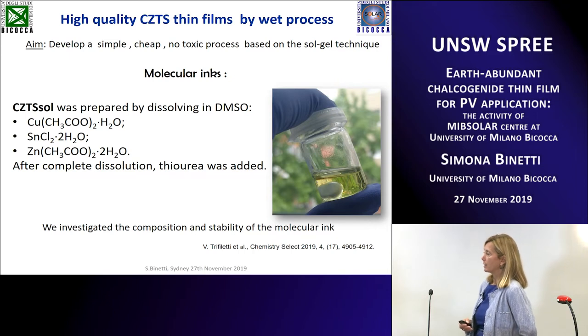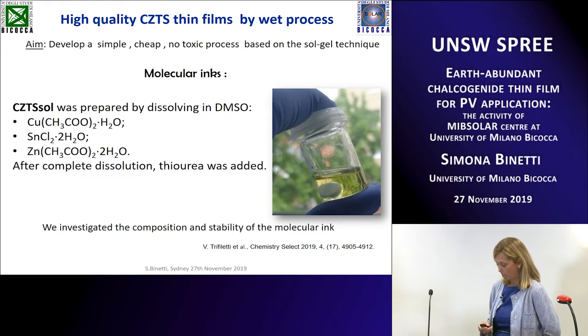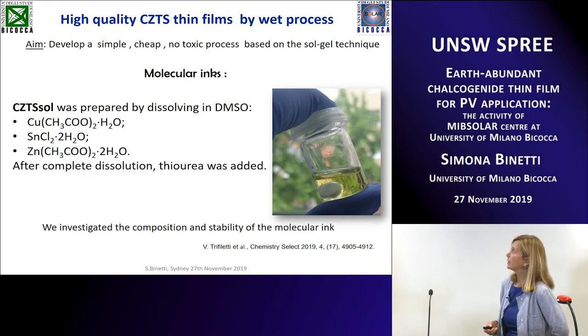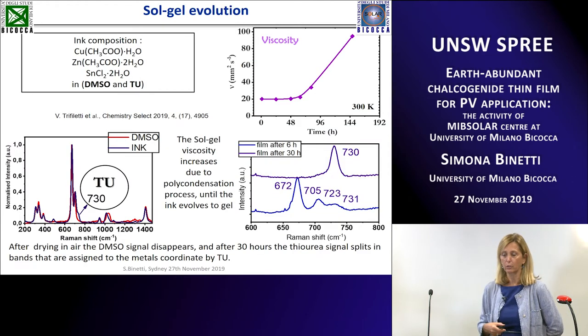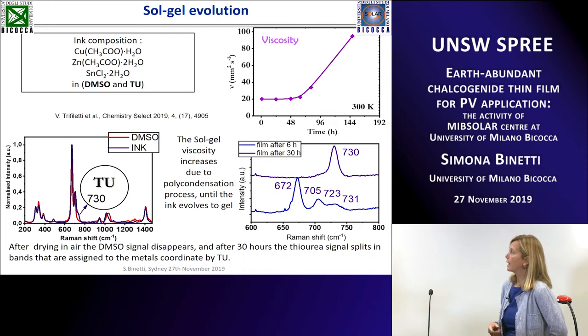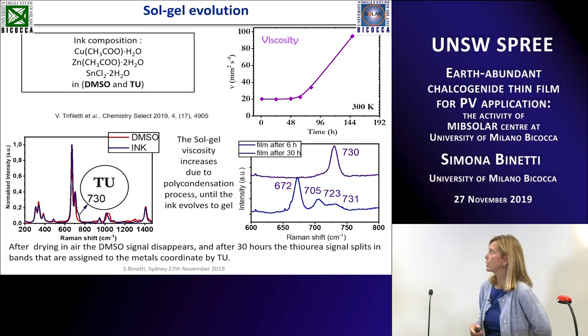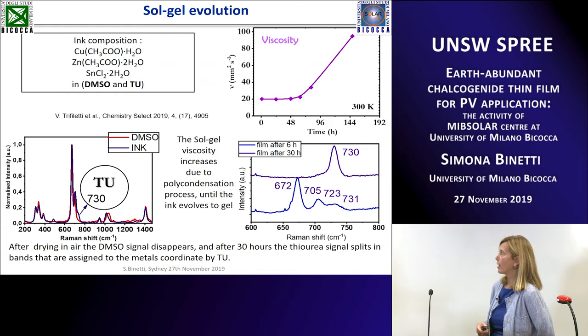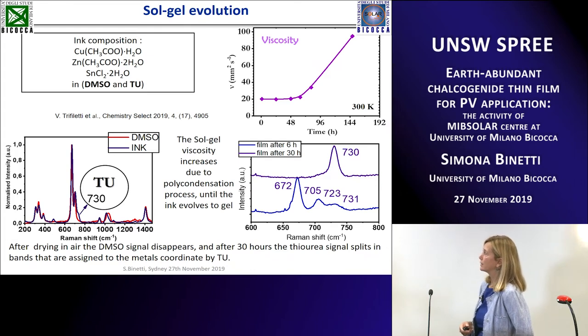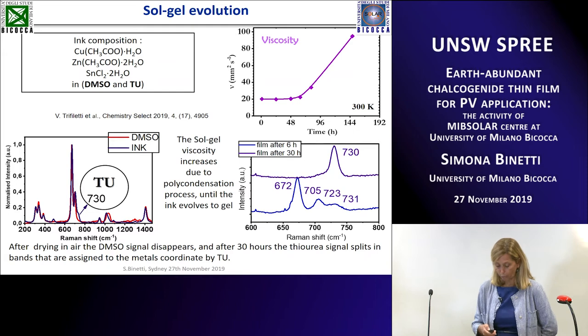Then we studied, of course, the composition and the stability of our molecular ink before depositing it on a substrate. And we have seen that, of course, there was a change in viscosity over time. The sol-gel viscosity increases due to a polycondensation process until the ink evolves to the gel. And we followed this evolution by Raman, and we have seen that at the beginning we have just the signal related to dimethyl sulfoxide, then this signal disappears, and the signal related to thiourea is much more visible, and there are also some signals that indicate that the thiourea is coordinated by the metals, and this is very important for the further formation of the Kesterite thin film solar cell.